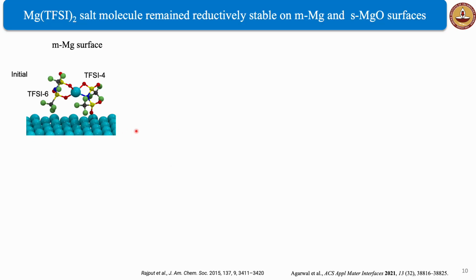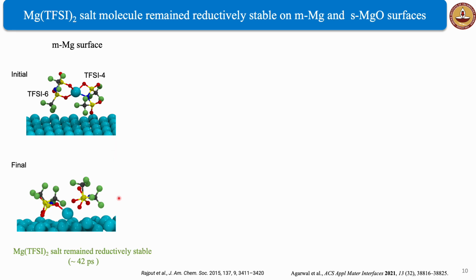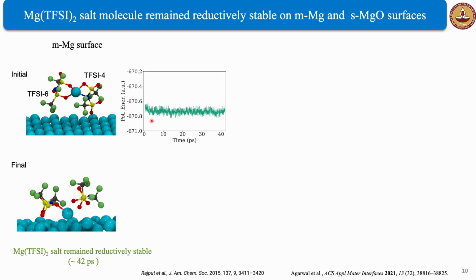First, we check the stability of the Mg(TFSI)2 salt on the metallic Mg surface. Here, the salt consists of two TFSI anions. One forms a four-membered ring with the Mg2+ cation, hence named TFSI4, and one forms a six-membered ring, hence named TFSI6. We found that during the NVT simulation, both the TFSI anions remain reductively stable on the metallic Mg surface. Also, the system didn't exhibit any major variation in potential energy, indicating the absence of any major structural change such as bond formation, bond dissociation, or lattice distortion.